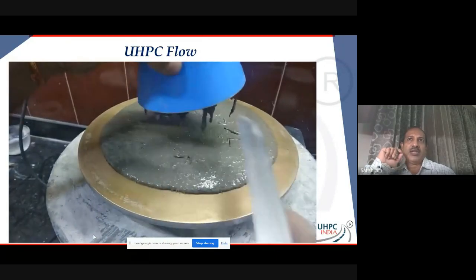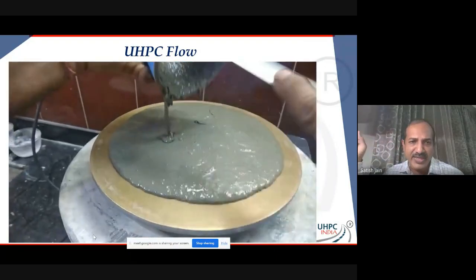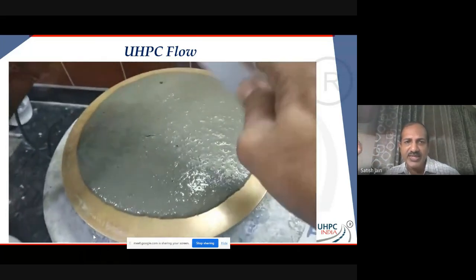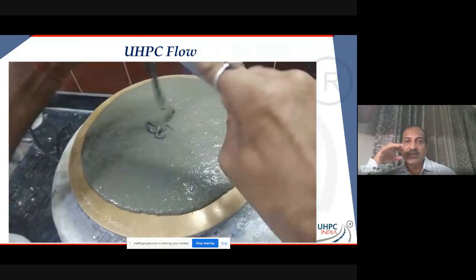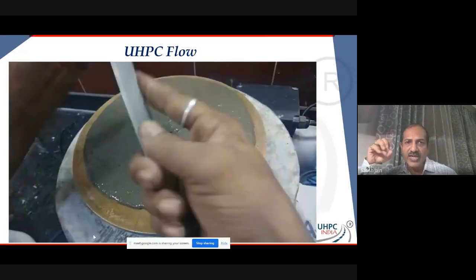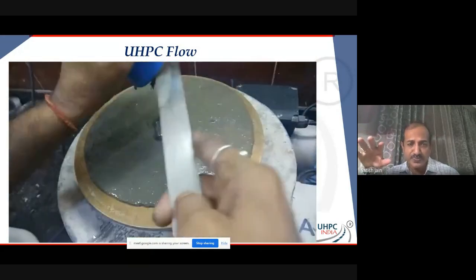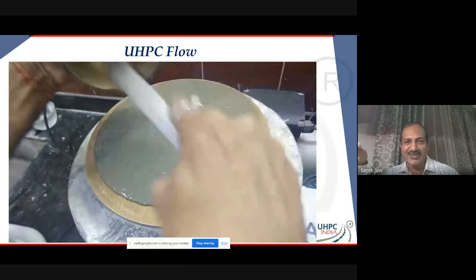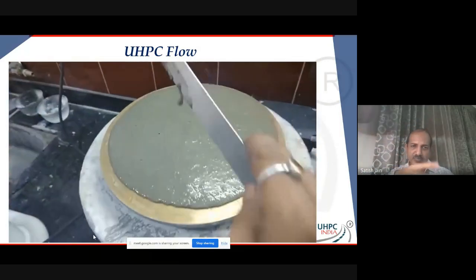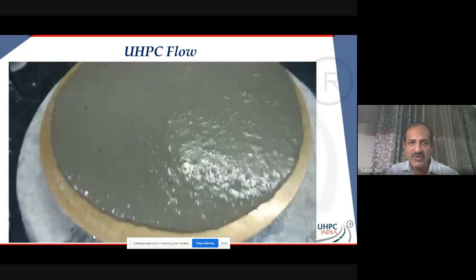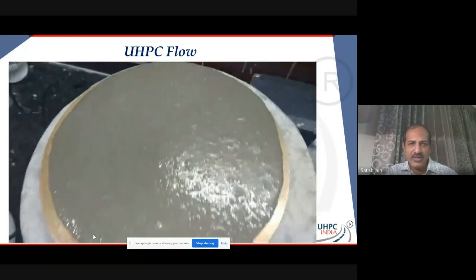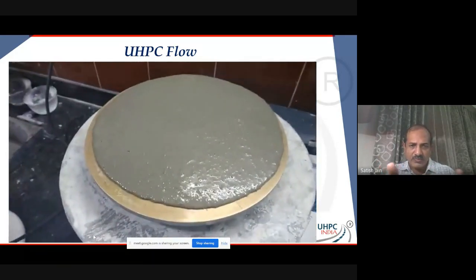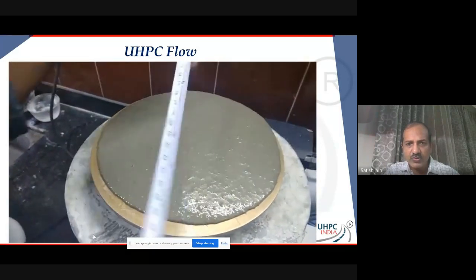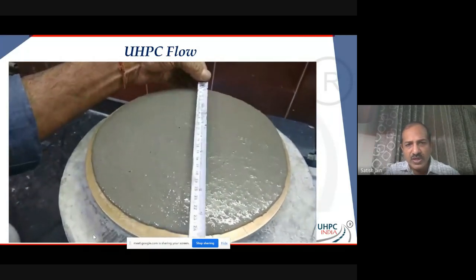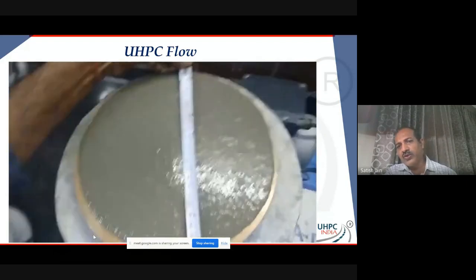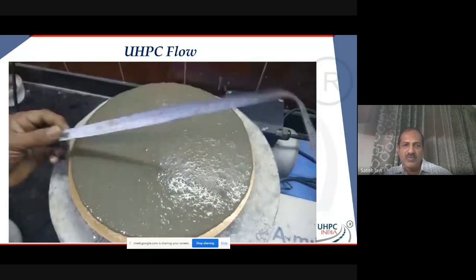ASTM C1856-17, which is for the entire testing and characteristics of UHPC, not just flow, all the material characteristics. The flow comes from there, and you can see that this table, its maximum is close to about 275 or so, yeah, 24 centimeters, so 240 mm of flow on this particular mix.